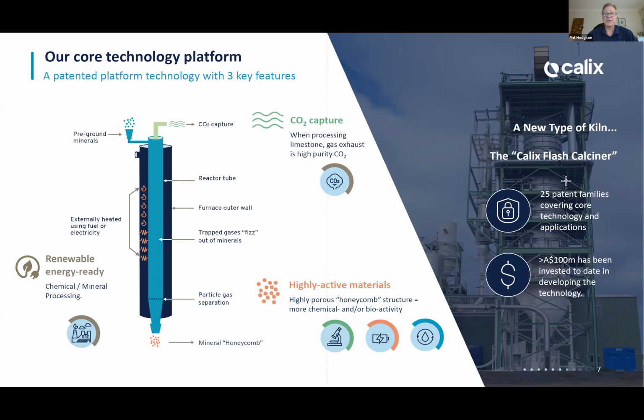And so you can imagine with our technology, the heat's on the outside, the heat medium, and the particles, the ground limestone or raw cement meal, are flowing down on the inside. The CO2 that's coming out makes its way back up to the top of the tube and comes out the top as a pure stream. So it directly separates the CO2 already for these industries. That's the first advantage of heating it our way versus in a standard conventional kiln, because the CO2 just goes up the stack gas and it's very difficult to separate at that point, whereas we just separate it because we heat it differently.